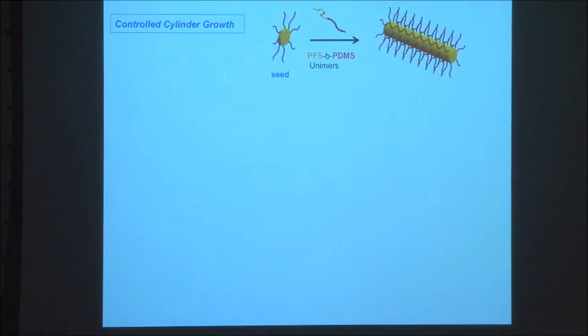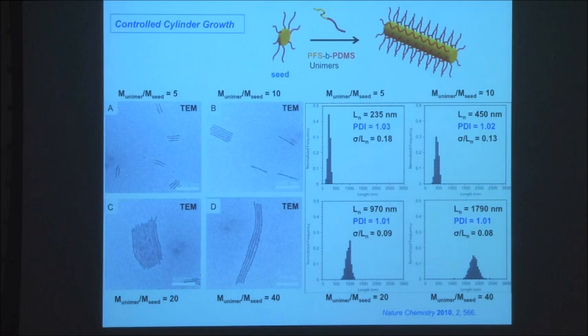You can then take these seeds and add more block copolymer in the form of unimers to the seeds, and the PFS block will then deposit on the ends of the seed, and the structure will grow. And if you carefully monitor this process, what you find is that you can control the length of the structures you generate. So based on the ratio of the unimer to the seed, this is the mass ratio. So when it's 5, you get cylinders that look like this. When it's 10, as you add more, they've grown. And here's 20, and here's 40.